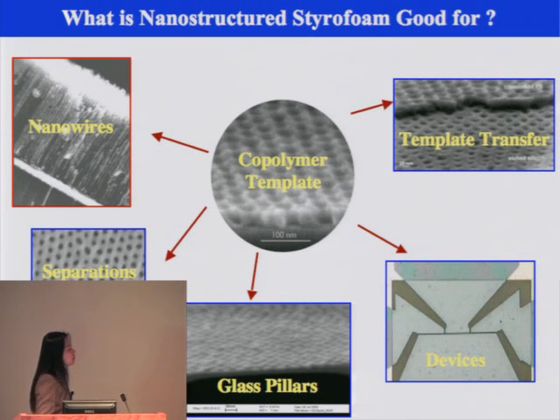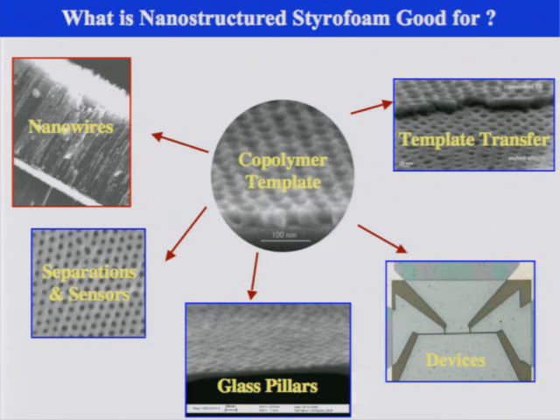Each individual pore can also be used as a nanoreactor. You can do chemistry in the confined geometry. In this case, you can grow silicon oxide into each individual reactor, and subsequently the matrix gets removed. What you see is glass pillars, hexagonally packed, with really good fidelity to the template.